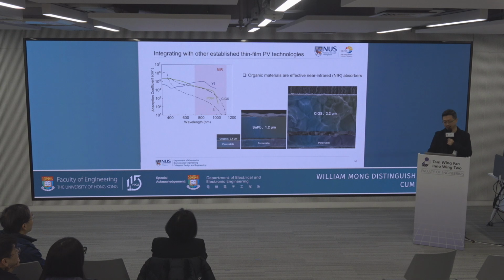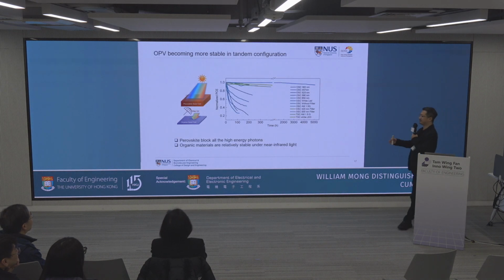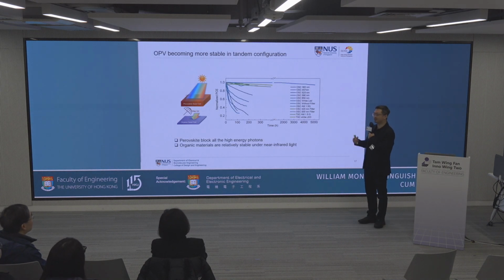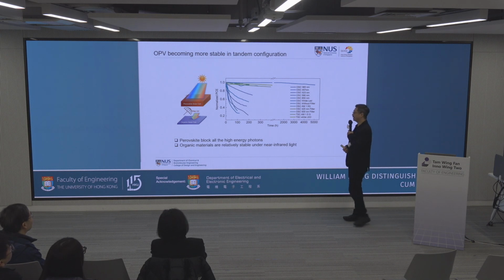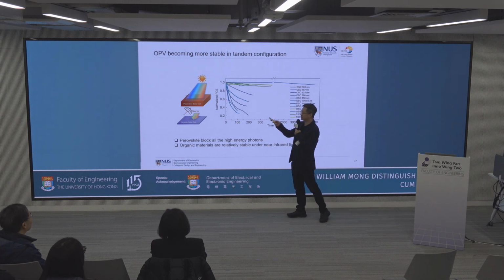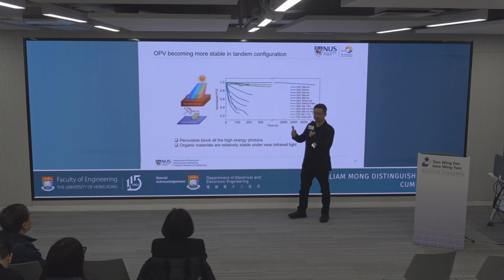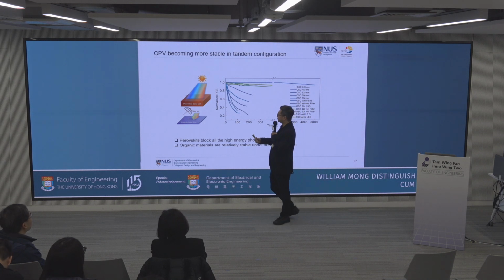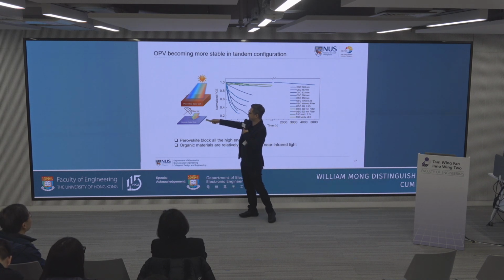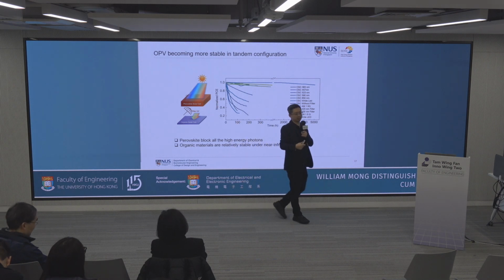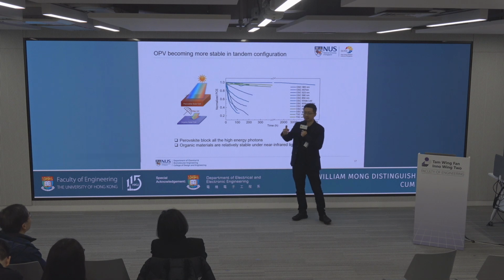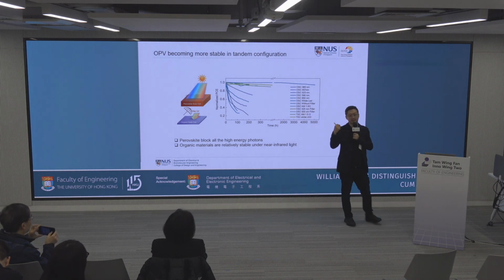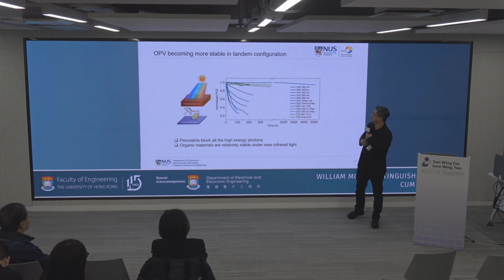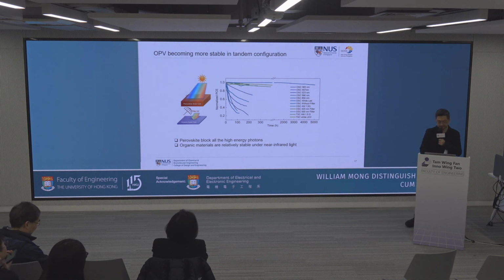red photons. And the organic cell has an issue with stability. Everyone worries about that. And indeed, the organic cell can degrade very fast under UV light, or the blue photons. So what we see here with the perovskite-organic tandem is that the perovskite basically filters out most of these blue photons. The blue photons and green photons will be absorbed by the perovskite. So perovskite acts as a filter. So all you have in the tandem is near IR light on this organic solar cell. So with that, actually the OPV has better stability.